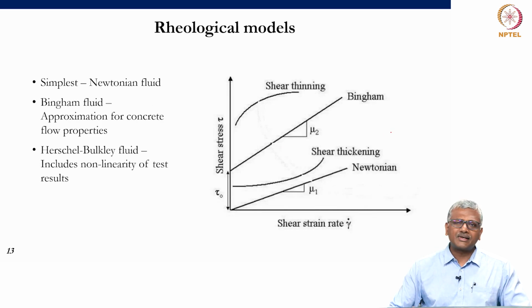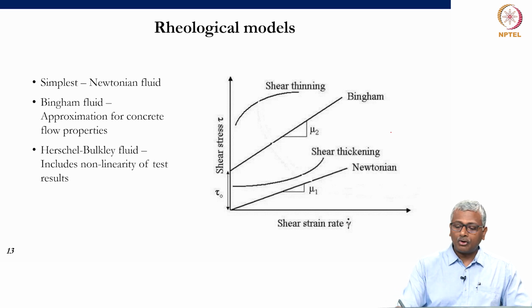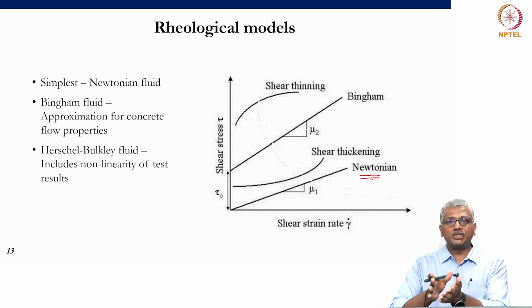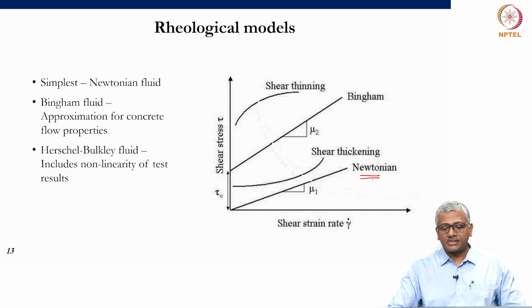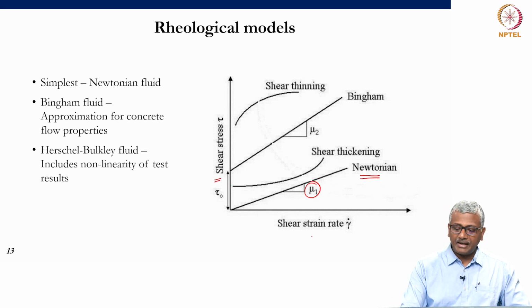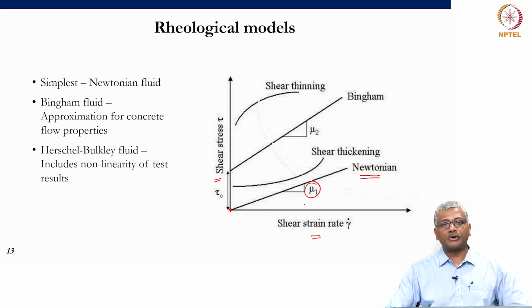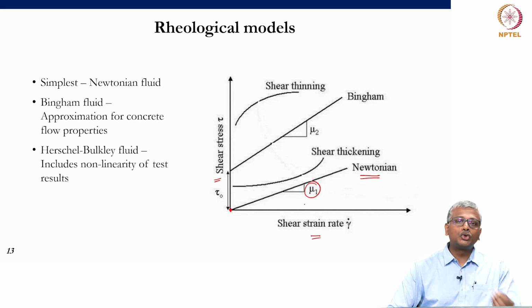And before that, let us look at some models which define flow behavior of construction materials and other polymeric gels and all kinds of flowable materials, right. You know that water follows a Newtonian behavior. As soon as you shear water, it starts flowing and there is a constant viscosity of flow, right. So, typical rheology plots are drawn between shear stress and shear strain rate, and a Newtonian behavior starts at the origin and is a straight line with a slope which is equal to the viscosity of the material. Water, oil, all of these things are viscous with a Newtonian behavior.